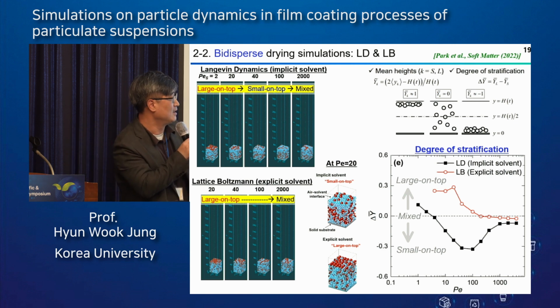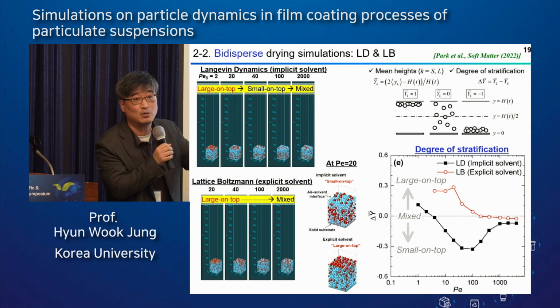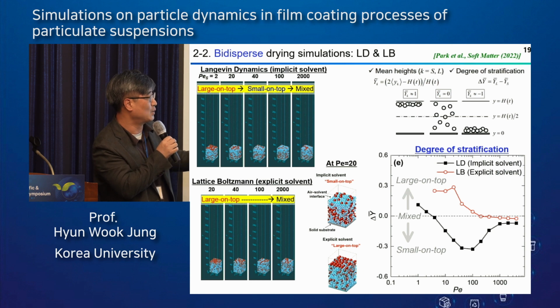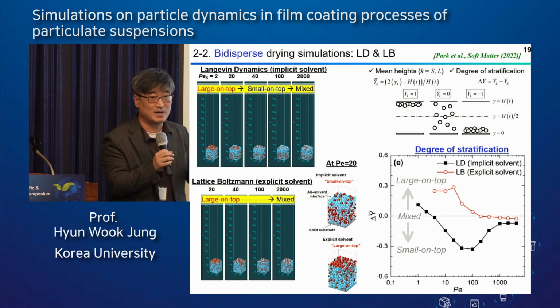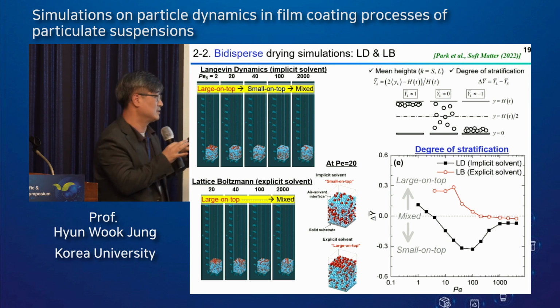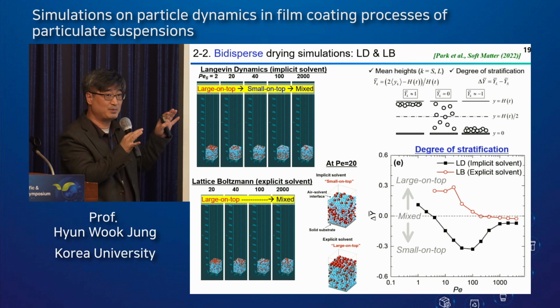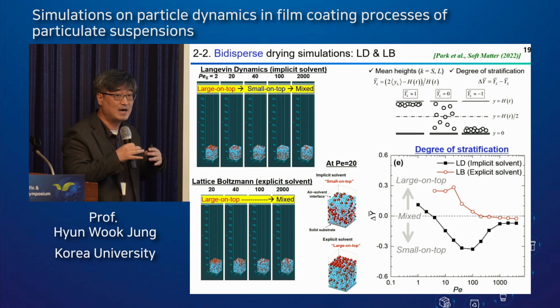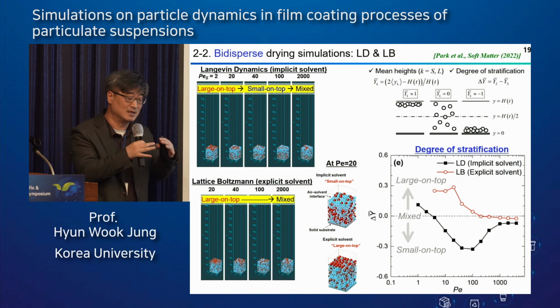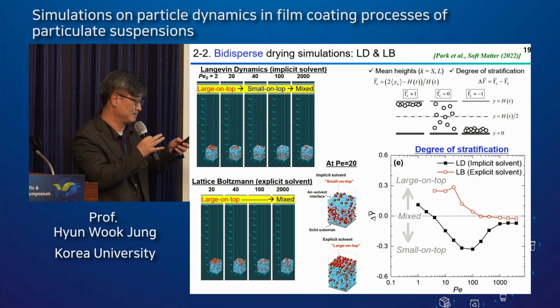So in that case, the implicit solvent method without hydrodynamic interaction showed large on top, small on top, and mixed case with increased Peclet number, and the LB case with hydrodynamic interaction showed the large on top, just mixed case, suppressing the small on top stratification due to the hydrodynamic interaction between the large particles, solvent, and the particles.